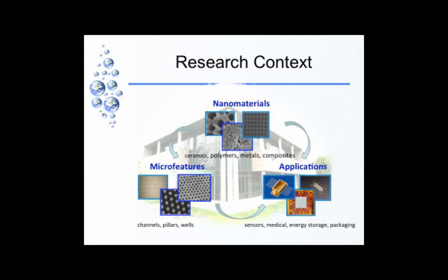But when you put fillers in there, powders, they can block flow, right? And so you want stiffness, but you don't want to block flow. You want permeability on the one hand, and you also want to have stiffness. And so the cellulose nanoparticles allow us to do that. And so it turned out that this is a good combination to try to do that.